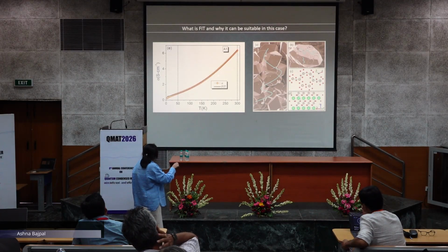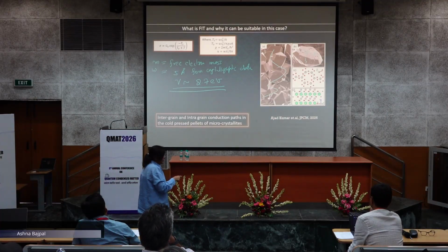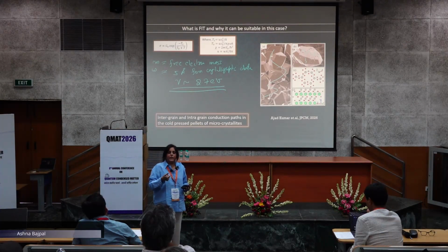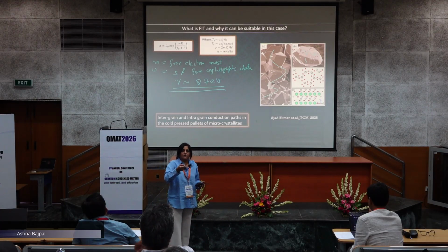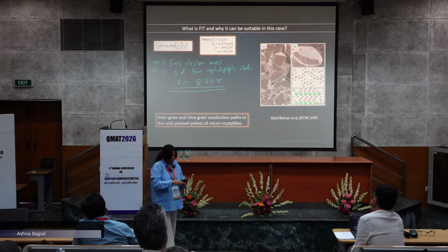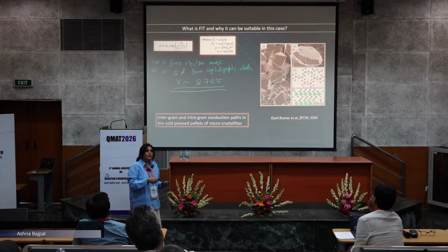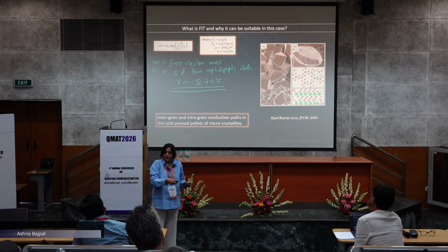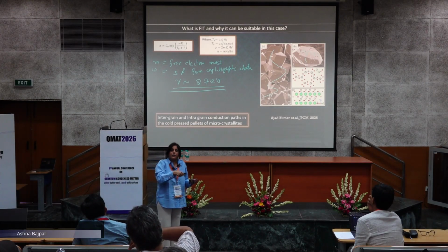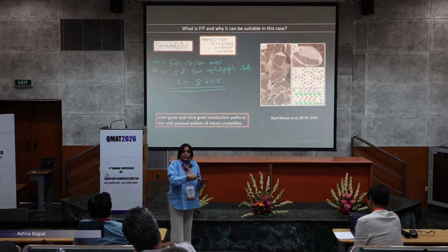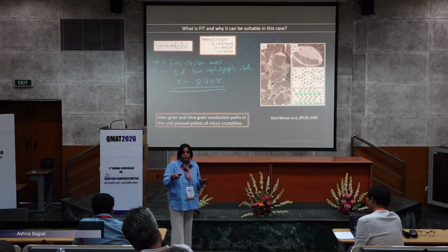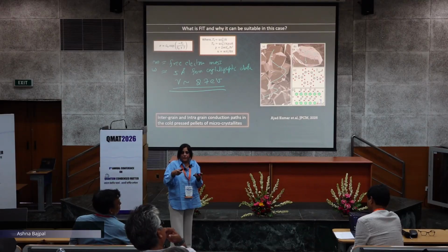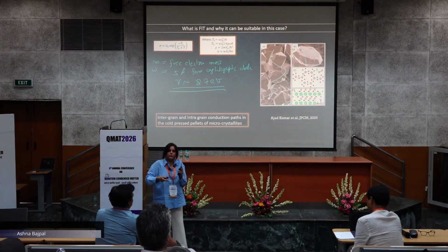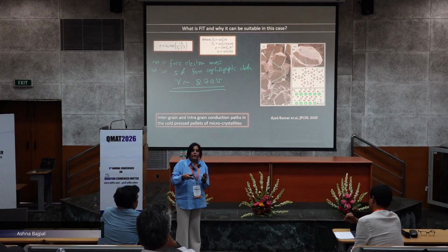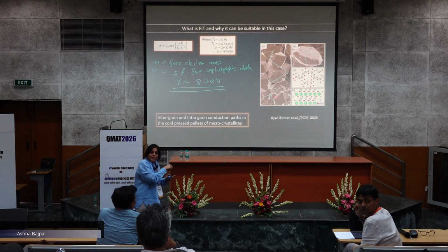To do this, from the parameters which we derived from the fitting, we tried to get some estimate of the numbers. So taking the free electron approximation as a first approximation. It may not be the free electron mass, but as I said, in all other dirty systems, disordered semiconductors as well as mesoscopic conducting grains, people start with the free electron mass and estimate the width of the potential barrier, which is the width of the insulating layer, and the height of the potential barrier. One could estimate reasonable parameters.